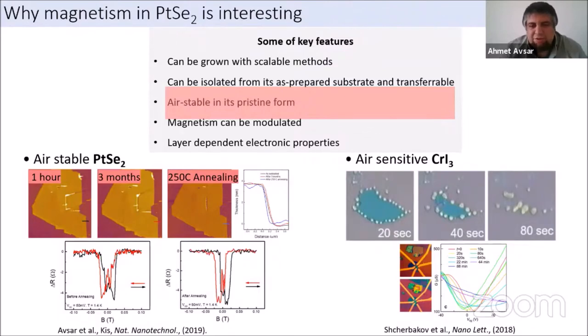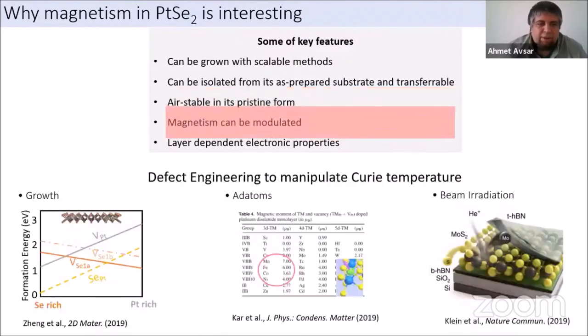So if you have chromium iodide, and if you isolate it and expose it to air, in 80 seconds, as you can see here, it completely degrades and disappears. And even if you encapsulate it, the encapsulation is only protecting it for several hours, even its properties changing along the way.